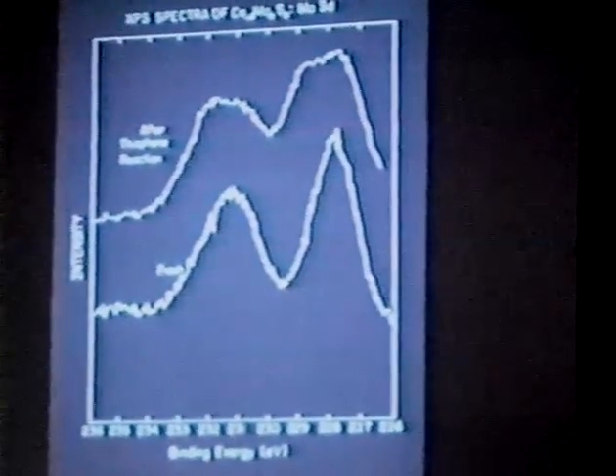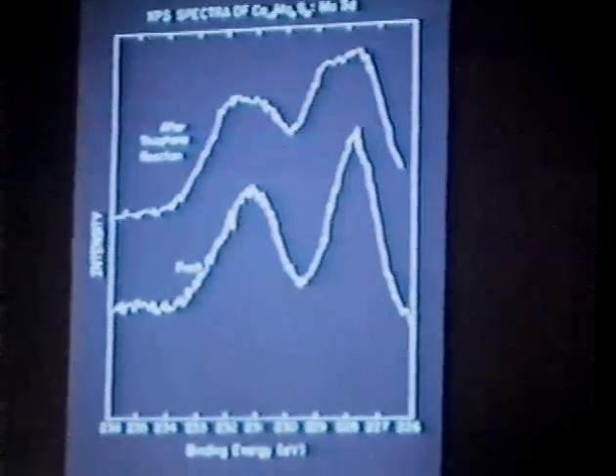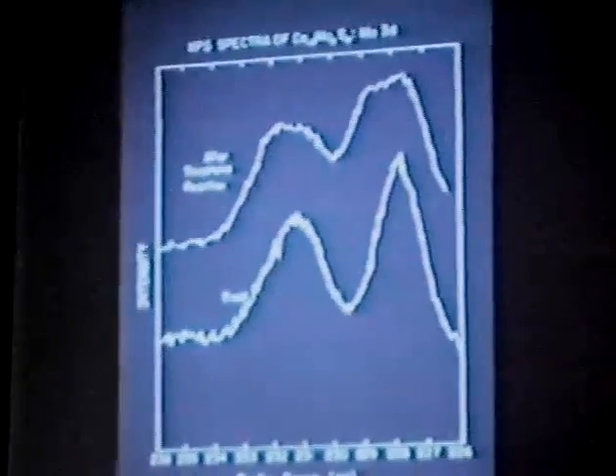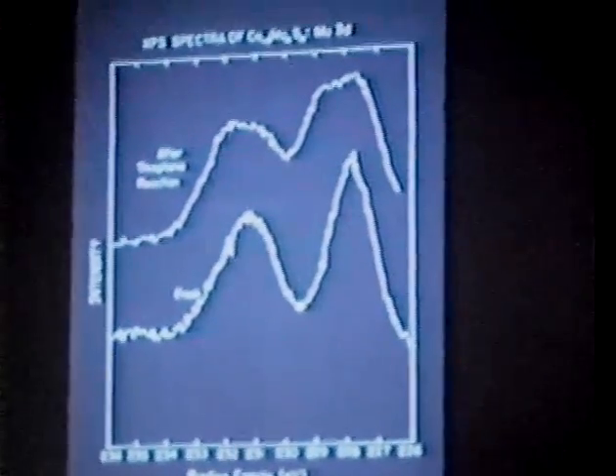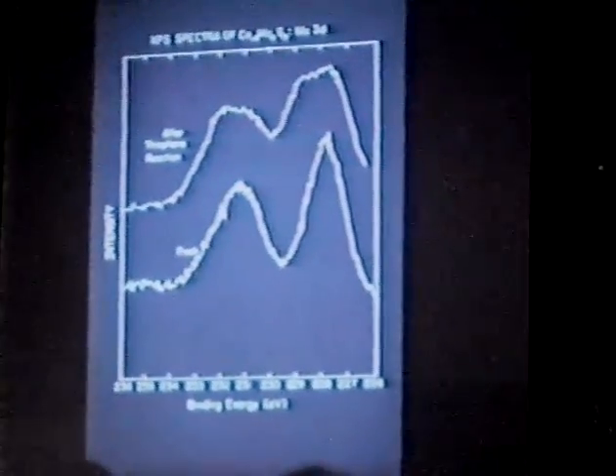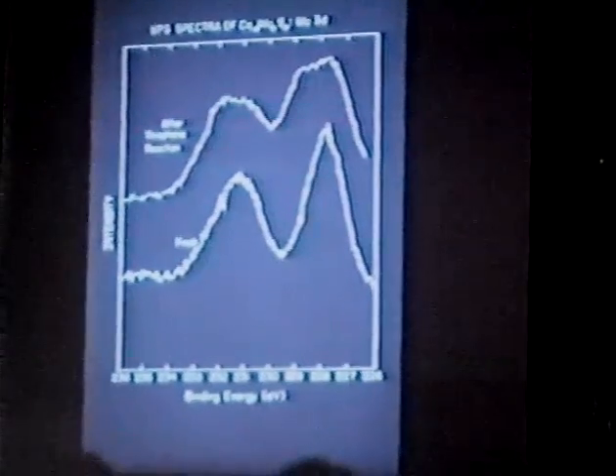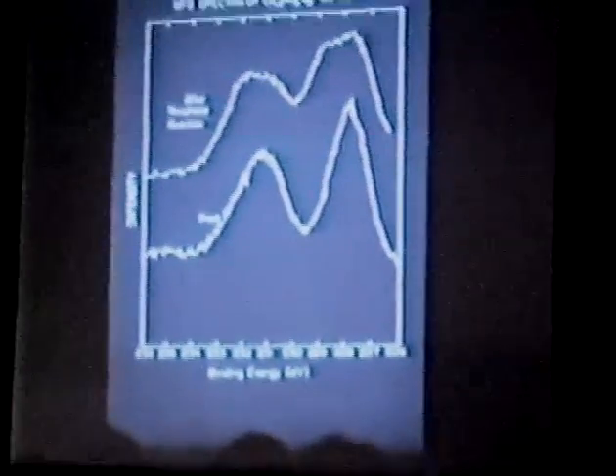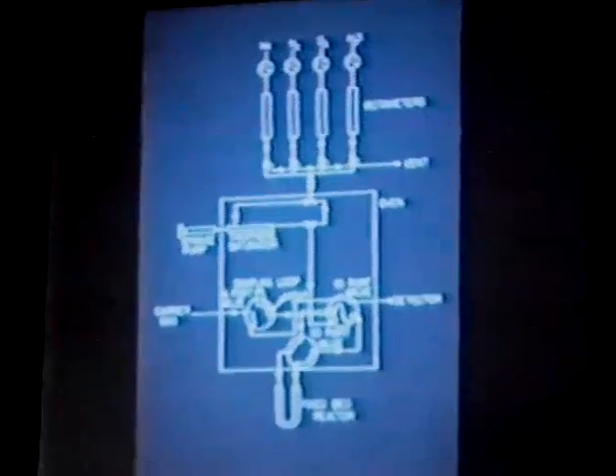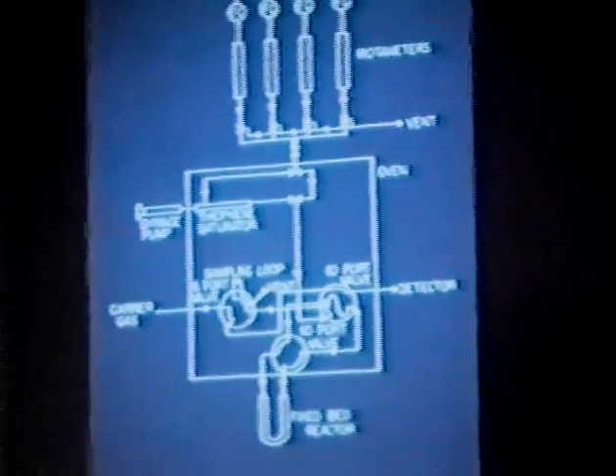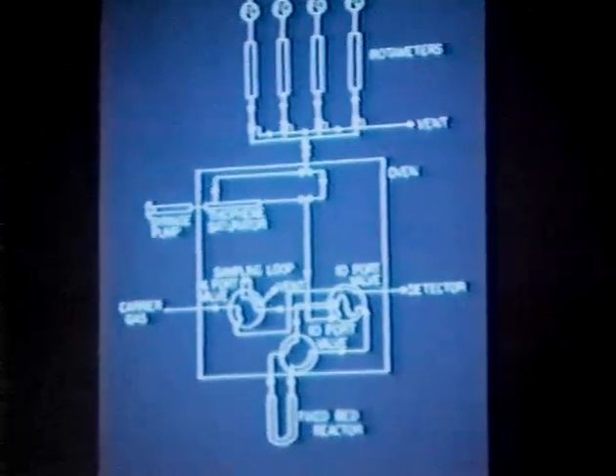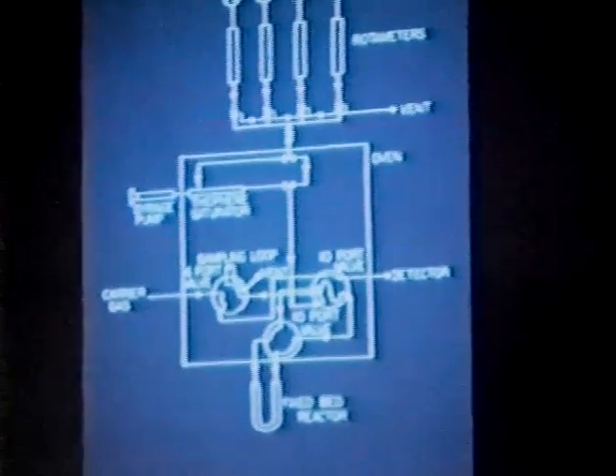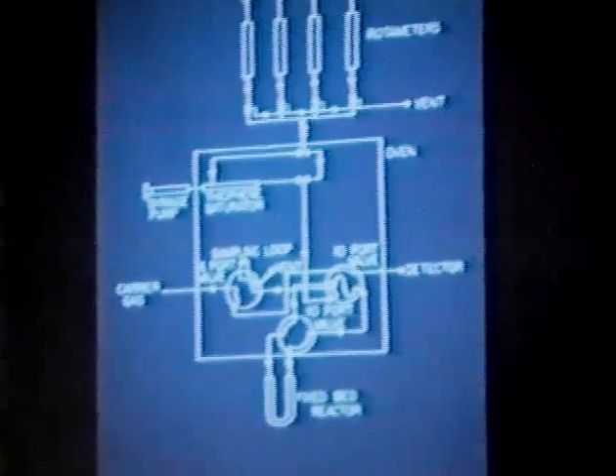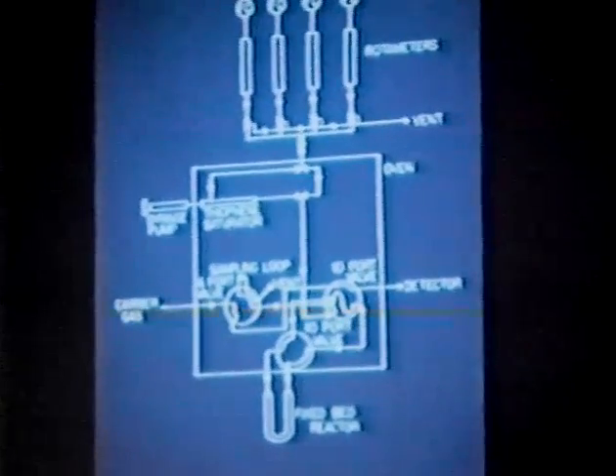But what I want to leave you with is the idea that these Chevrel phase compounds are very stable. You would think that structurally, from the way they were made, and our results with a lot of characterization really show that very few of them undergo bulk transformation to any other phases. And what you put into the reactor is pretty much what you get out of the reactor under our studies for thiophene hydrodesulfurization and benzothiophene. This is a small illustration of our microreactor type system. Thiophene studies were done at about 400 degrees C. Benzothiophene, which I won't tell you very much about today, studies were done between 250 degrees C and about 500 degrees C. Studies were done for as long as 40 hours in some cases.